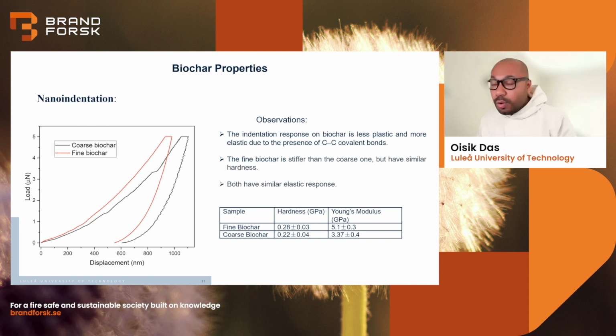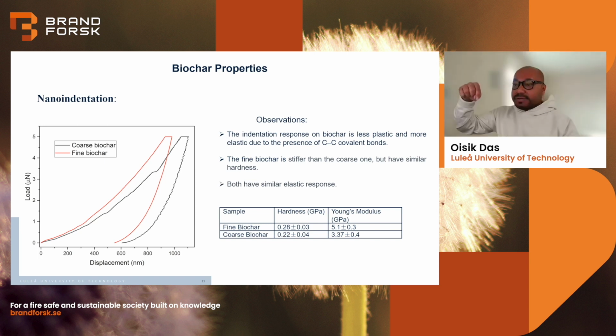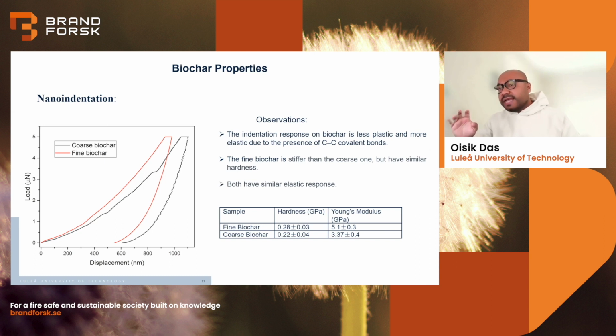Basically, a known amount of load is given, and an indenter, so it's like a pin, goes down and presses on the biochar particle. Depending on the hardness or softness of the biochar particle, the pin will go deeper and deeper, and that pin will leave an impression mark. So based on the surface area of the impression mark and the load, we can calculate the hardness, and we can get a load and displacement curve that we see on the left. And from the slope of this load displacement curve, we can get the stiffness.